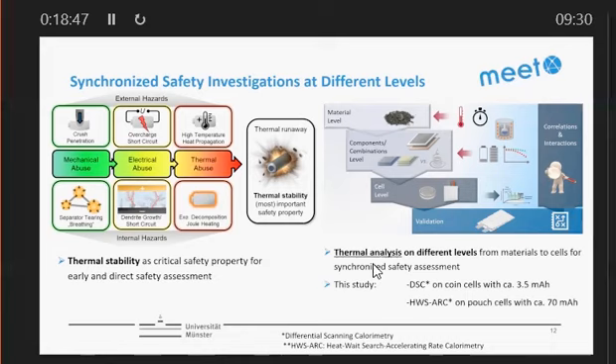That means we did several measurements to find out whether this is representative of what we are measuring. And we used DSC on coin cells with a relatively small capacity, and heat-wait-seek accelerating rate calorimetry on pouch cells with about 70 milliampere hour.